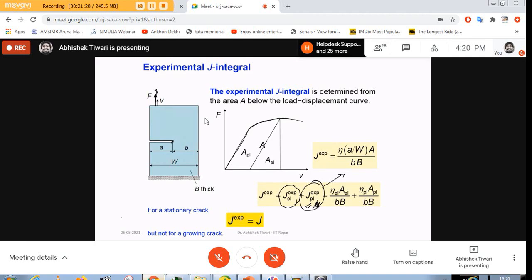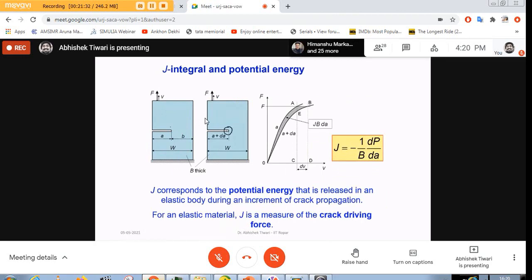But if the crack grows, then what happens? Imagine this specimen has an initial crack length of a, and then the crack length increases by a small amount, delta a. So the crack has grown. What happens to the material point which is here? This material point was initially there, and therefore it must have had a high stress value, some finite value. Now the crack has grown and that material point is no longer attached to the point on the other side, so the stress value there is 0. This means there has been an unloading, and unloading is not allowed in this concept.